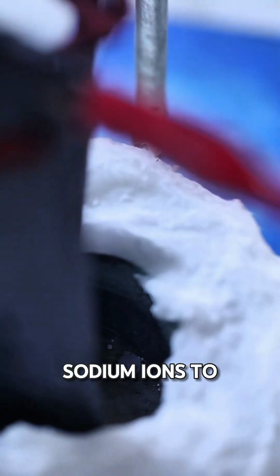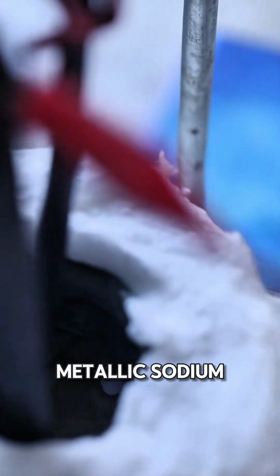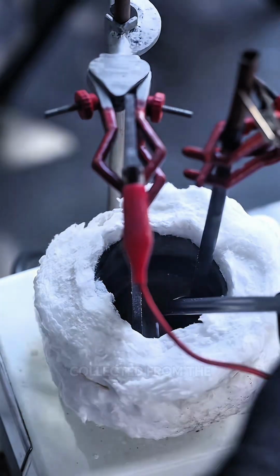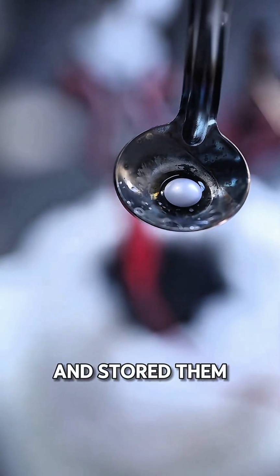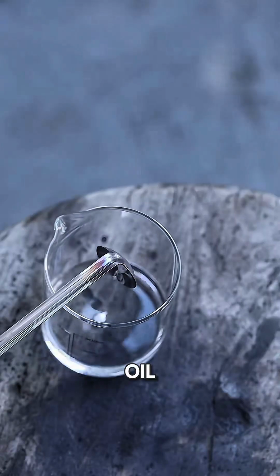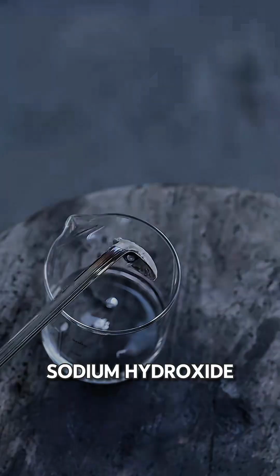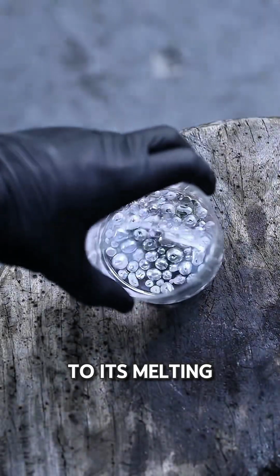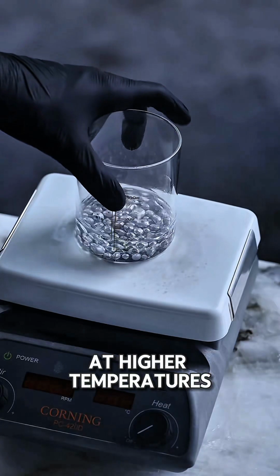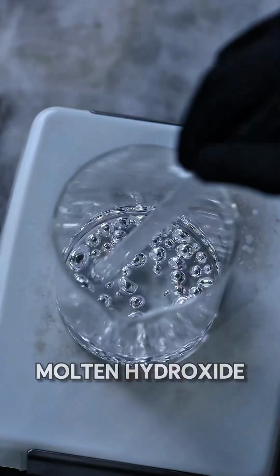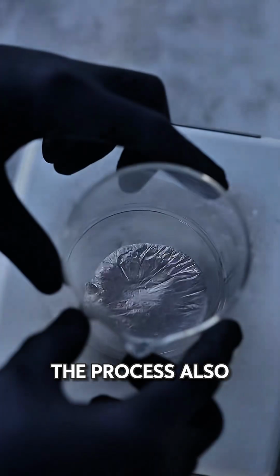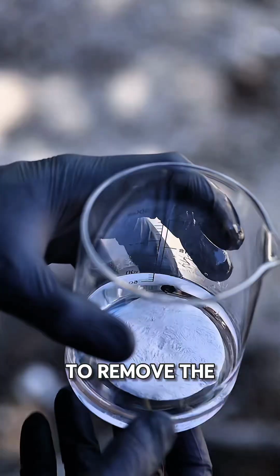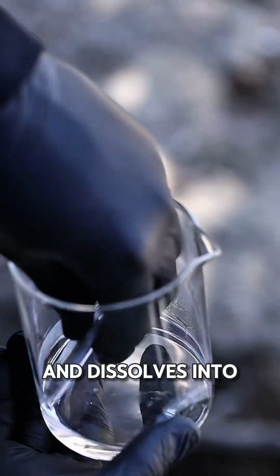It allows the sodium ions to be reduced to metallic sodium, which forms droplets that can be collected from the surface. I gathered several of these droplets and stored them in a beaker filled with mineral oil. The electrolysis of sodium hydroxide only works close to its melting point. At higher temperatures, the sodium dissolves back into the molten hydroxide. The process also needs to be paused occasionally to remove the water that forms at the anode and dissolves into